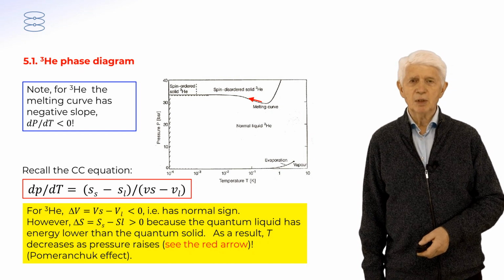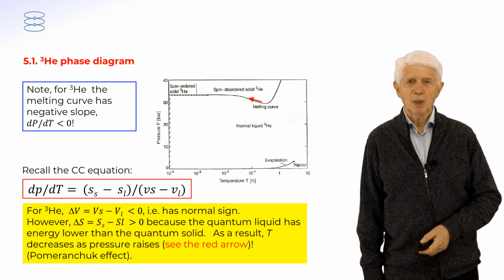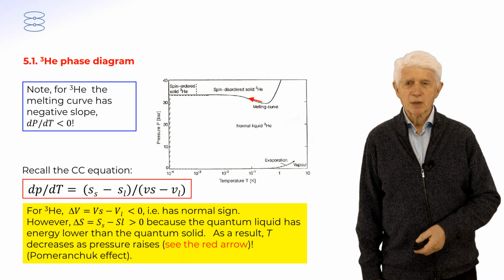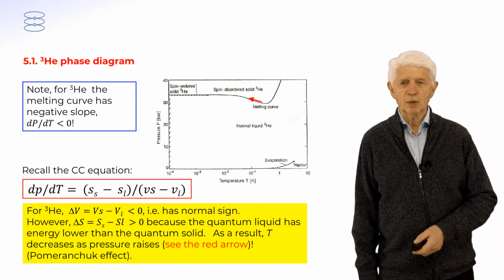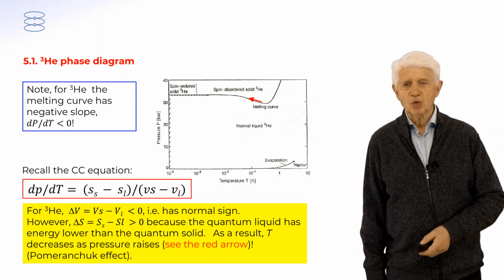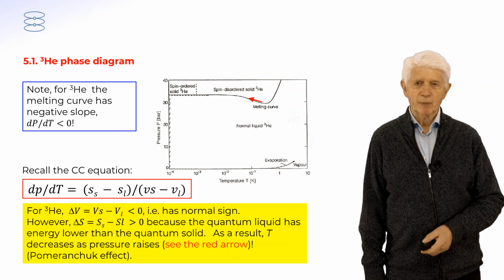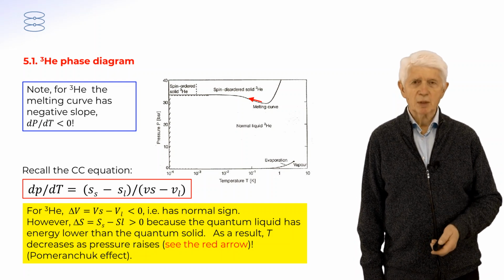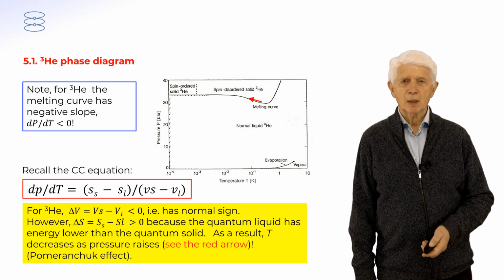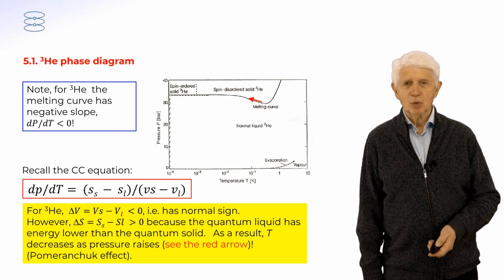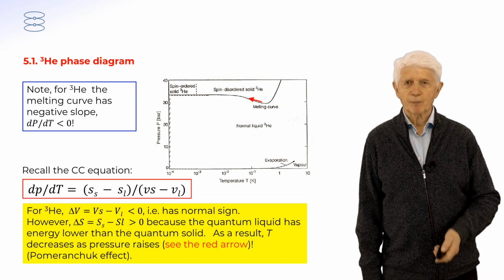And this indeed can be realized in practice, and for many years was one of the ways to achieve lower temperatures, by the so-called Pomeranchuk effect, by raising the pressure. And this is illustrated by a red arrow. Increasing the pressure, you go to lower and lower temperatures.